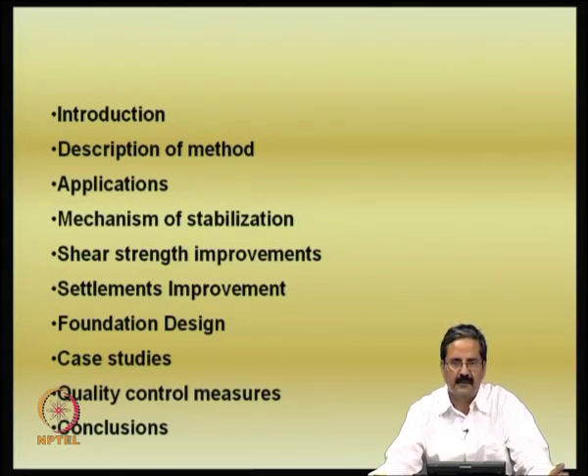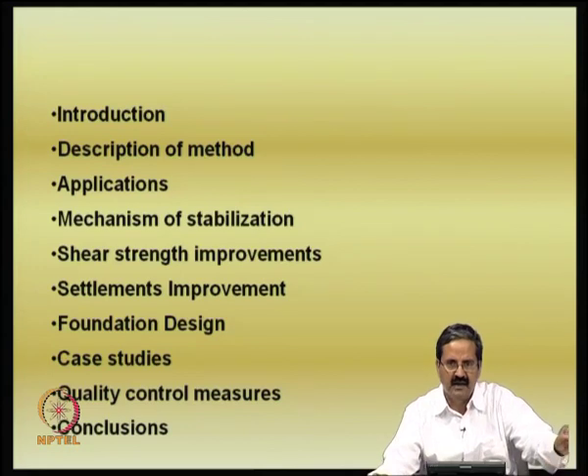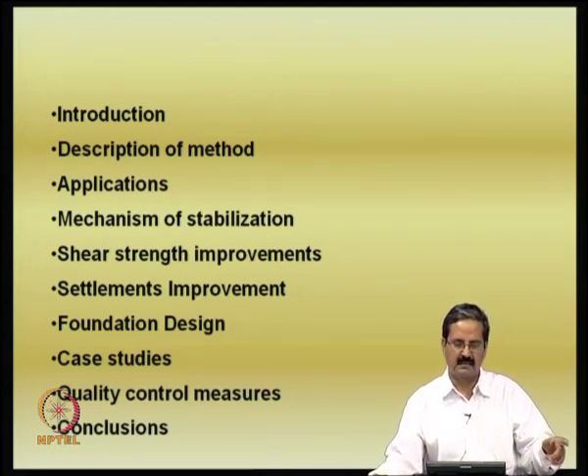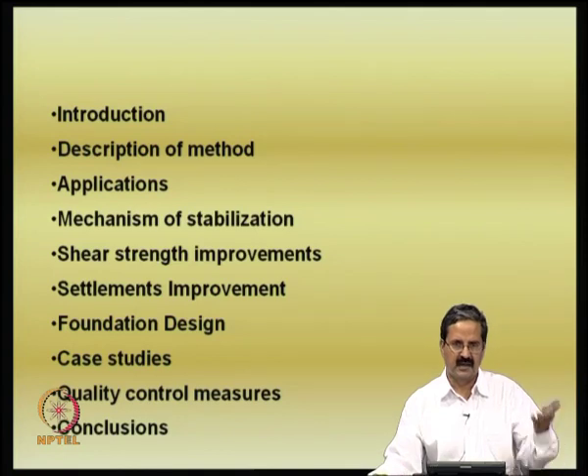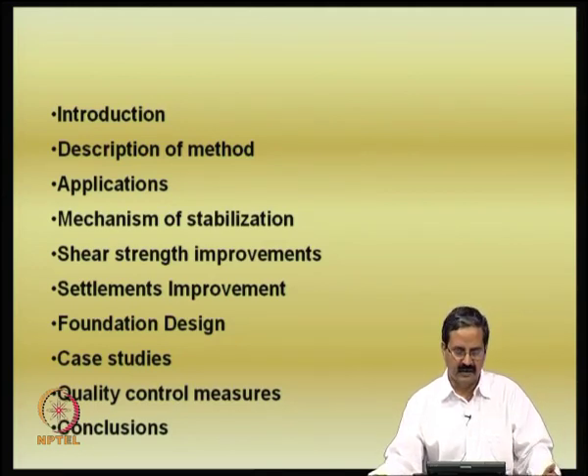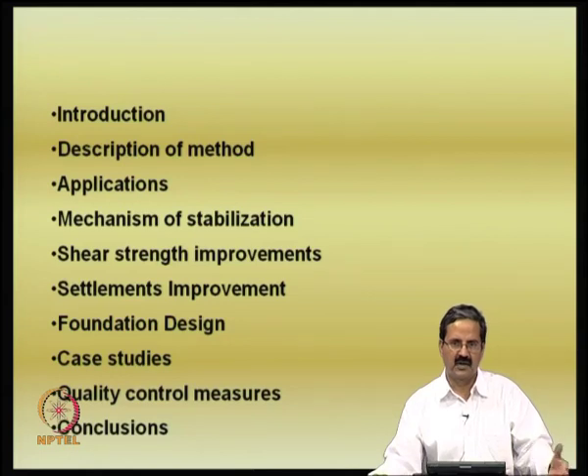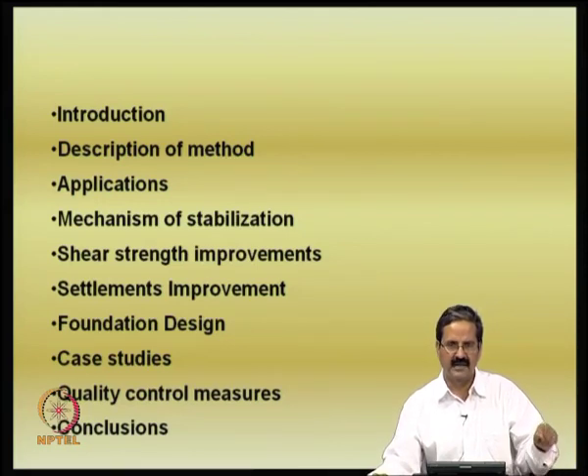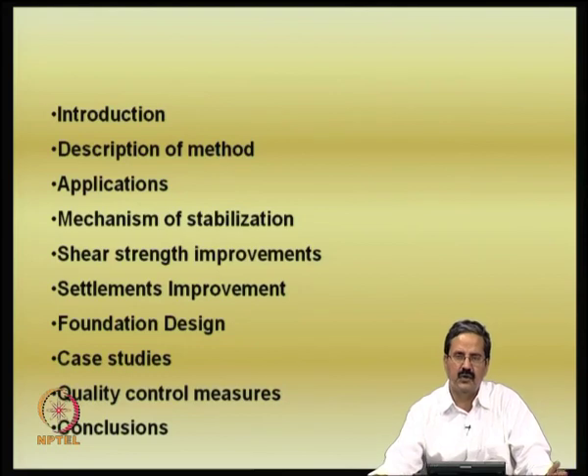The classical case of lime treatment itself: lime treatment is very effective if there is no sulphate in the soil. But if sulphate is present in the expansive soil, then it becomes worse. There are a number of tests one can do, and people have shown that if sulphate is present and you try to give a lime treatment, it cannot be effective. So if you want to make lime treatment effective, you should check whether sulphate is present. If it is not there, go ahead with lime treatment, and sometimes you need to add additives like fly ash or cement depending on requirements.